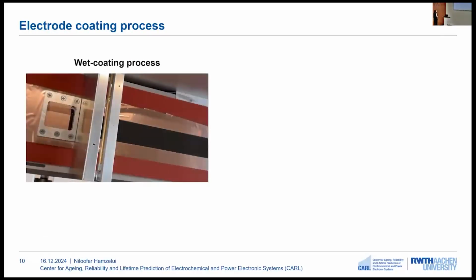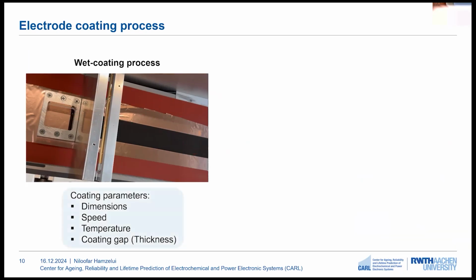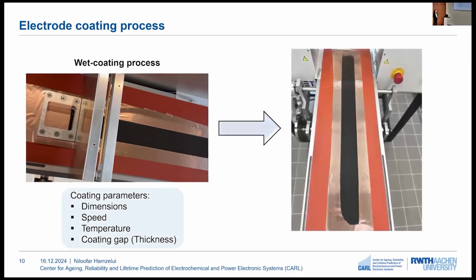So here is an image of the electrode coating process that I have used in the lab. Here in this drawbar, this is where the slurry goes, and by moving this plate with a constant speed, the electrode will be coated on top of the copper current collector. Different parameters such as the speed, temperature, or the thickness of the coating can be controlled in this step. And finally, we will see the final result, which is the anode, which is coated on top of the copper current collector.